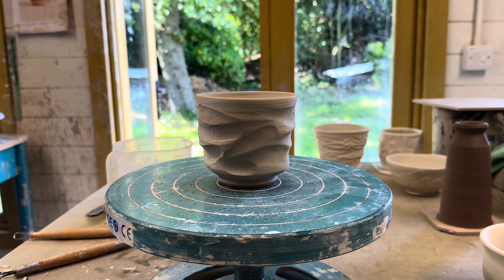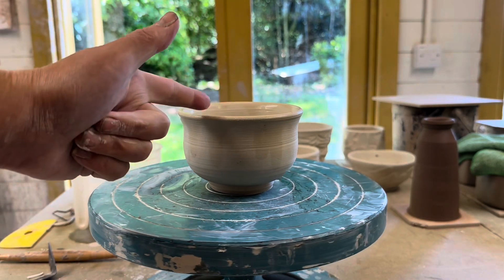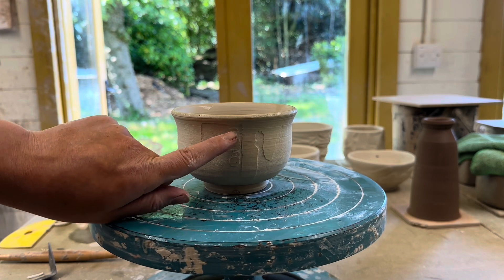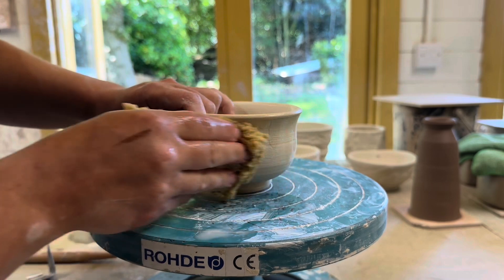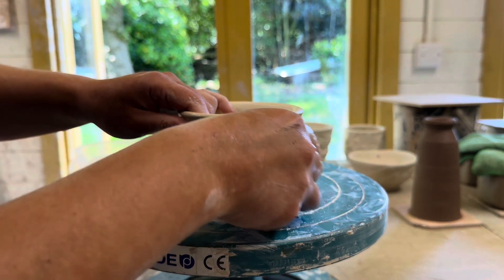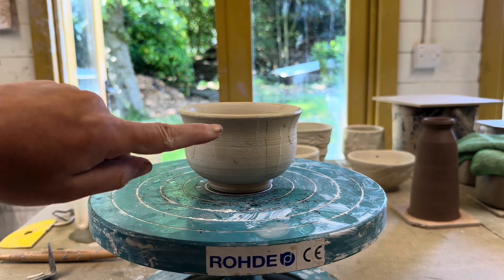I've painted shellac over the rim and let it drip down — I quite like how organic it looks. I wanted to do it on the rim so that when I sponge it away it won't disturb the rim like it did on my other piece. Where the drips are thicker it holds itself, but thinner drips start to wash away — you definitely need a thick layer of shellac. I'm spending time removing that shellac from the clay, which has grog in it. I might also try this on my other non-grogged piece to compare.